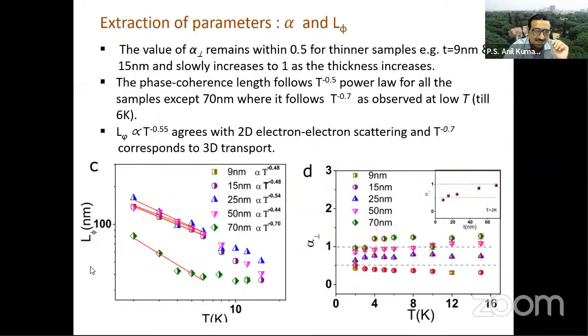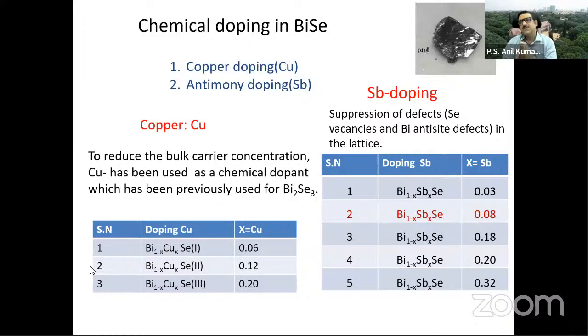So now with this understanding, we started asking the question, when we work with strong topological insulators like Bi2Se3, which is also self-doped, what do we do? In order to compensate for that, instead of bismuth we add antimony, and instead of selenium, we add tellurium to get the compensation doping so that we get a bulk insulating material. So we also started looking at the chemical doping of this material, and we dope with different materials.